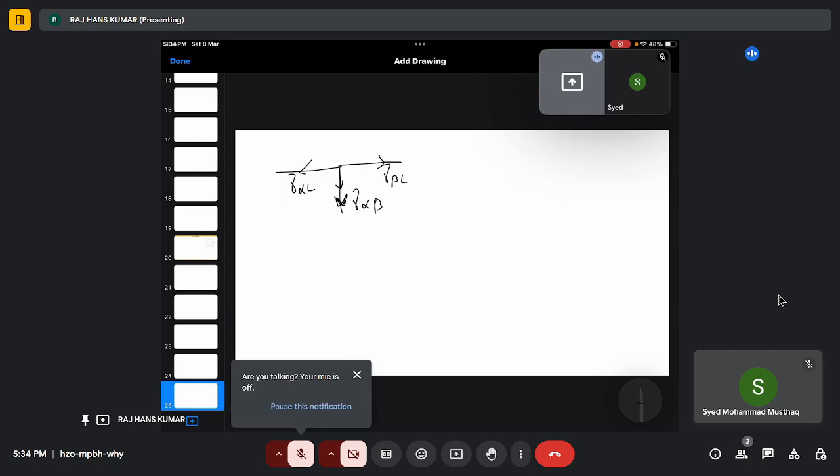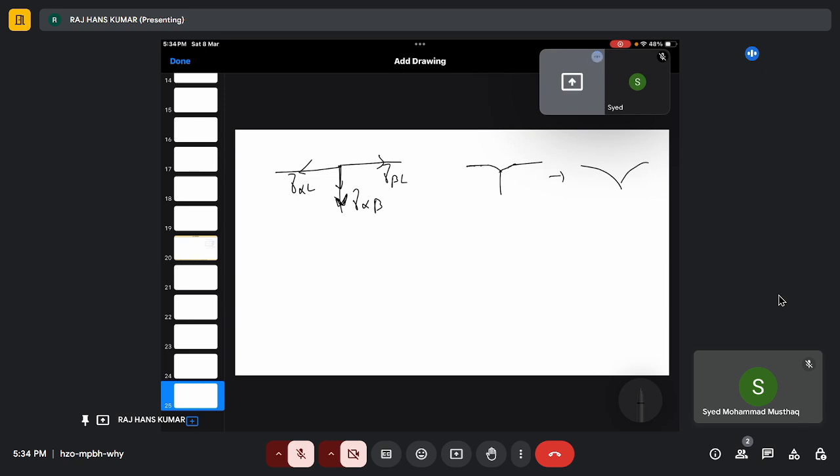downwards, and because of that, slowly, first there will be planar, and because it will drag a bit, again after some time, more dragging will form. So finally, you will have this columnar region where these forces will finally be balanced. So that is why this is a more equilibrium shape when compared to this. Now, that is all about the equilibrium.